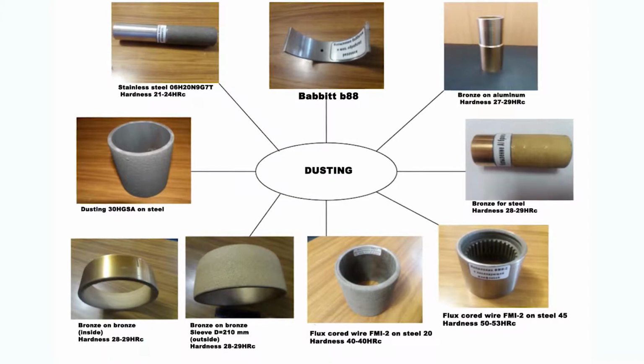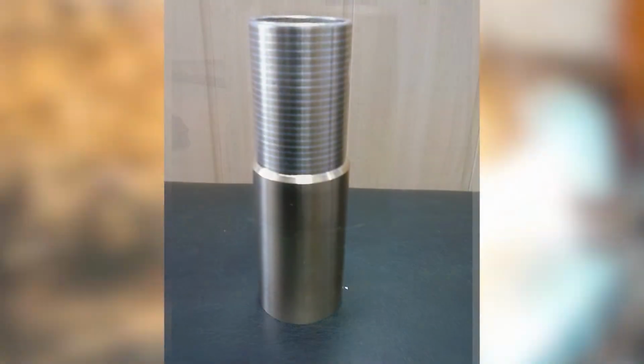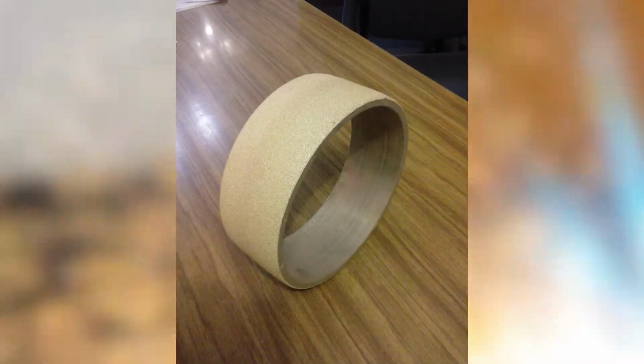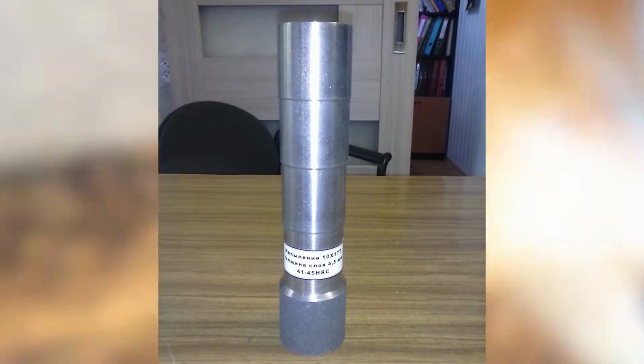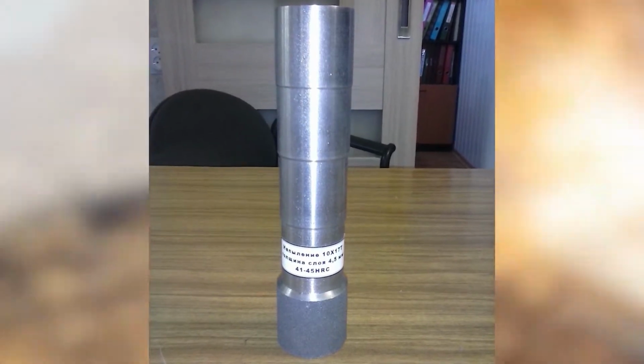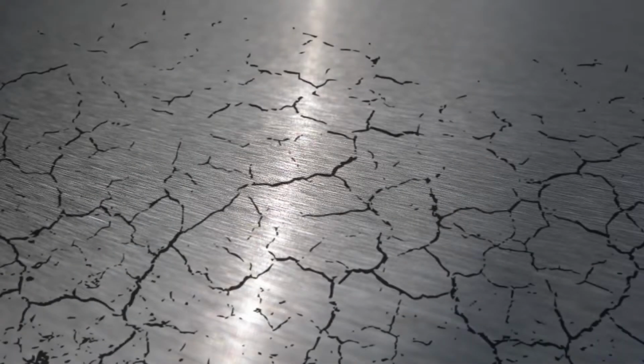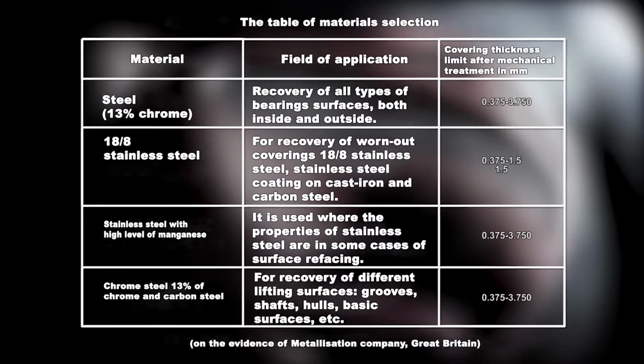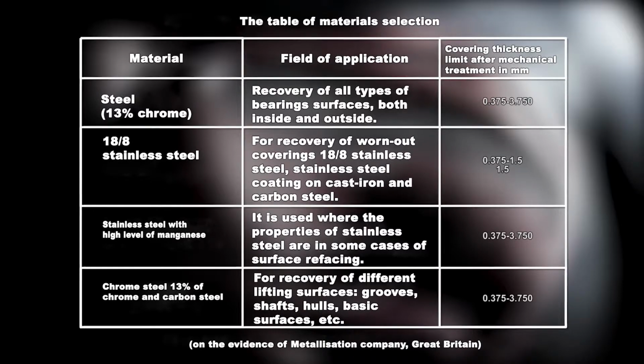Some examples of covering selection: all the materials applied during the gas-thermal spraying process have the ability, while getting cold, to compress. Due to compression, tension appears inside the surface being treated that may lead to cracking or cover separation. The level of compression depends on the material used. Studies have shown that 13% chrome steel has the lowest level of compression, and stainless steel 18-8 and carbon steel have the highest.